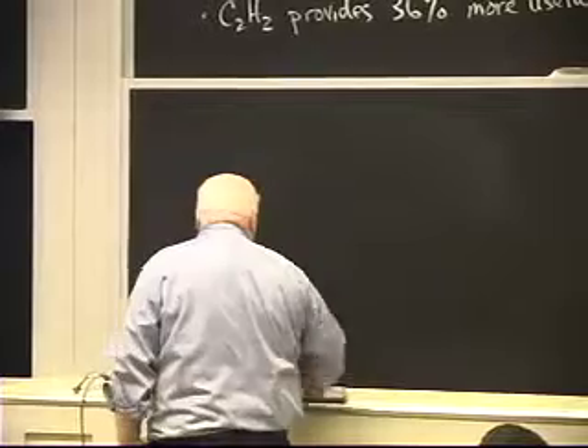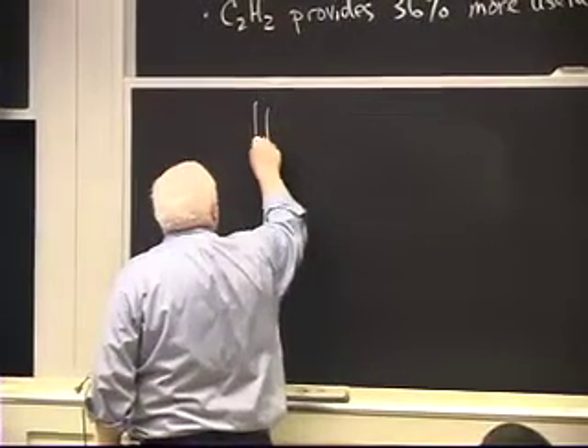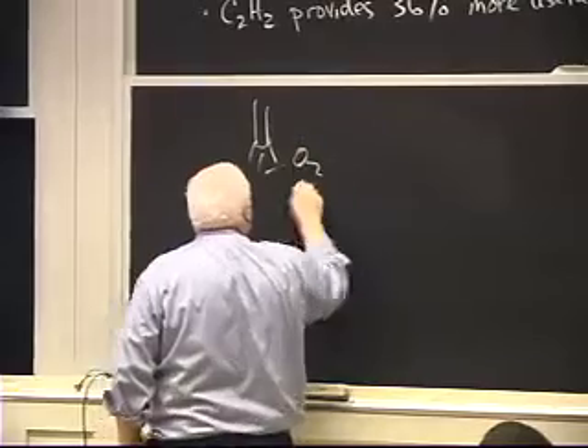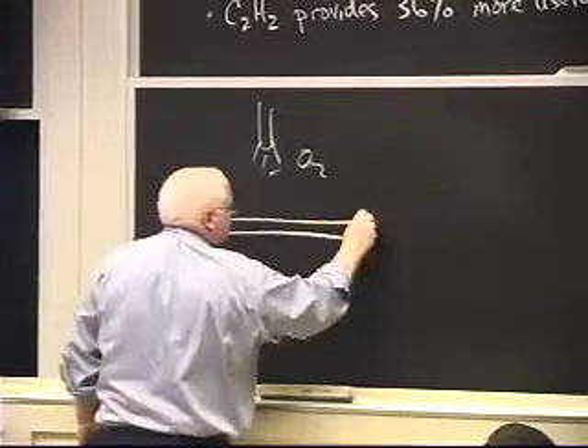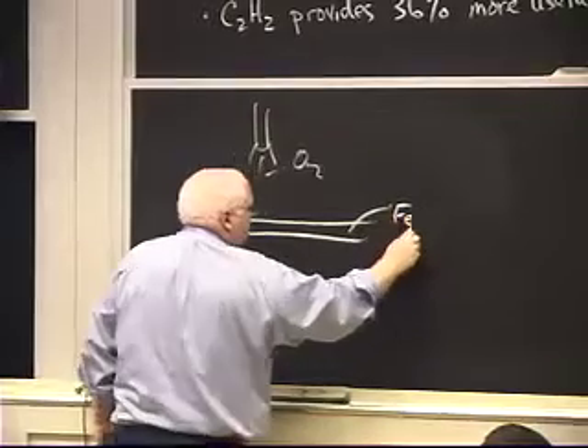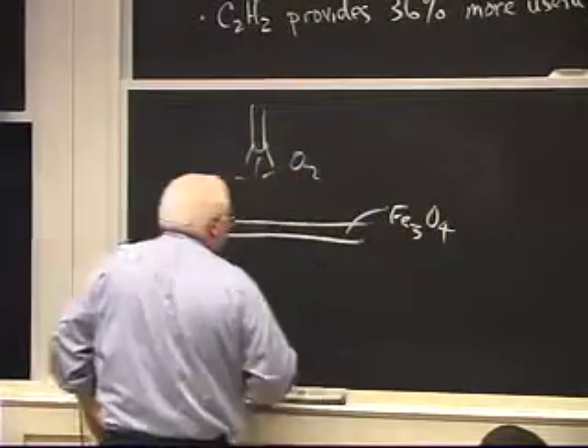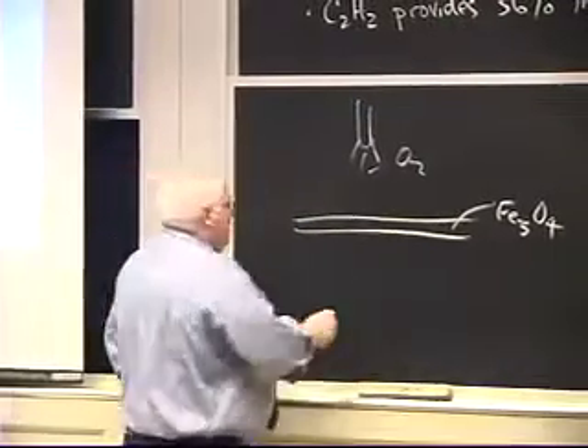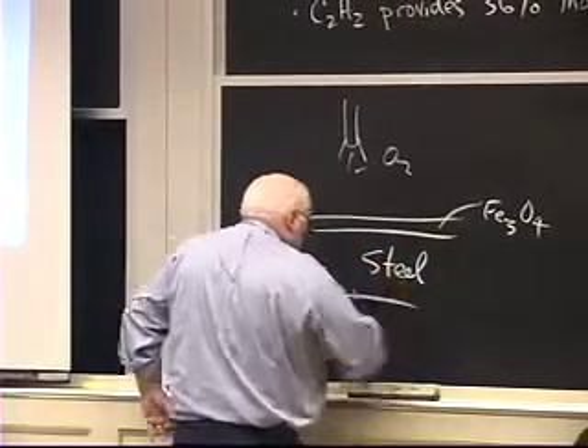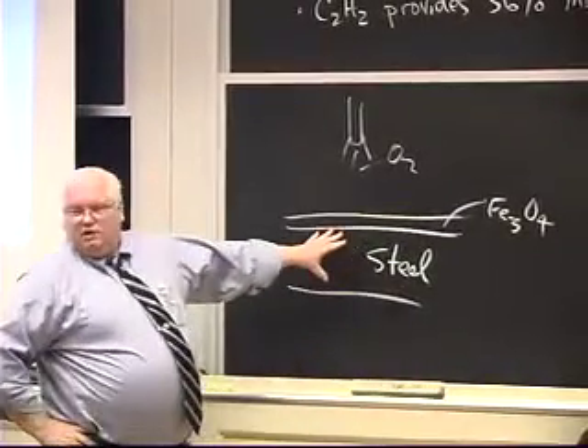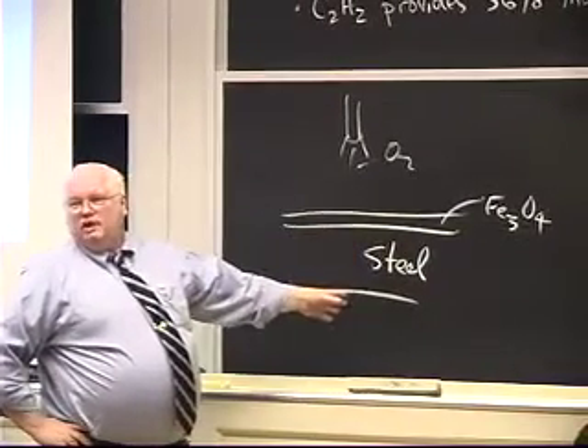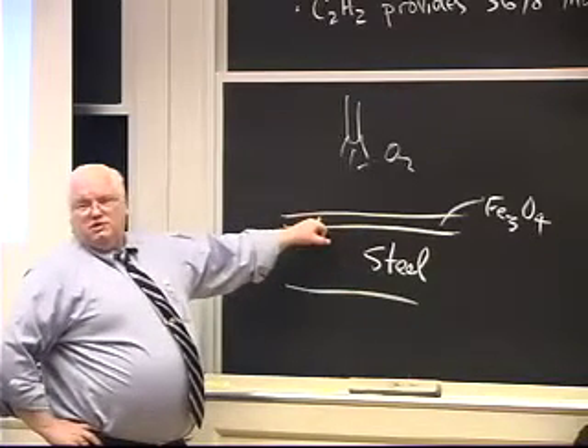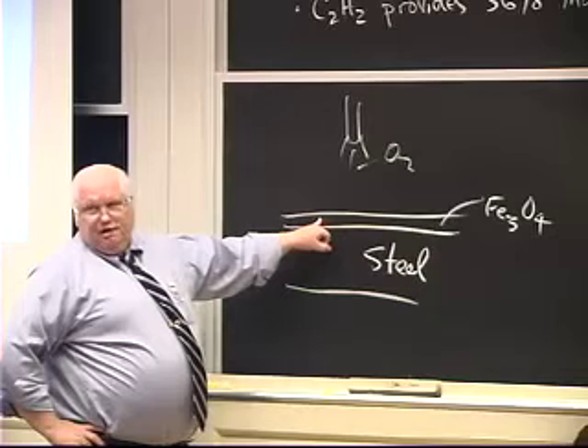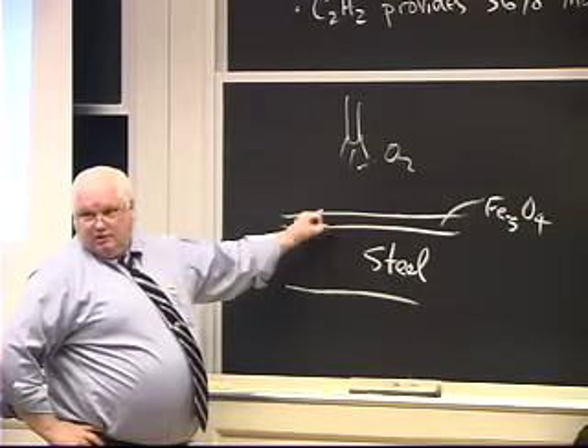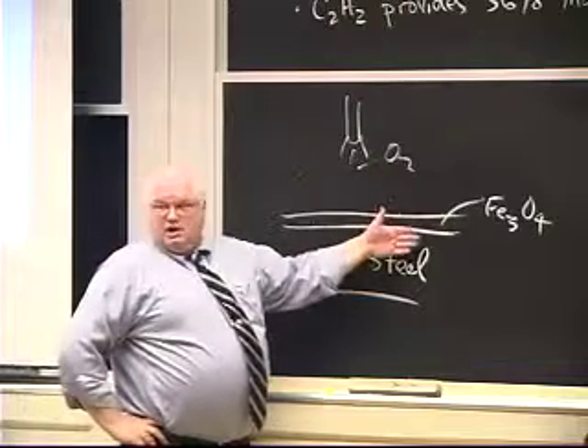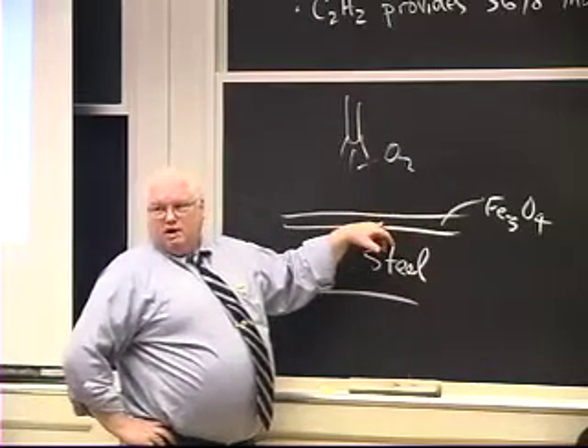Ordinarily, you have a problem of this gas boundary layer. In this case, a jet of oxygen is going to be hitting the surface of the steel. And the surface of the steel has a surface coating, and more likely than not it will be Fe3O4. It could be FeO, it could be Fe2O3, but this is the steel. And if this is coming out of a continuous casting furnace, this could be 12 inches thick, a piece of steel. And this iron oxide on the surface might be a few thousandths of an inch thick. Probably no more than 10 thousandths of an inch thick, a few human hairs thick. But basically it oxidized in the air, and you can't cut through the iron oxide.